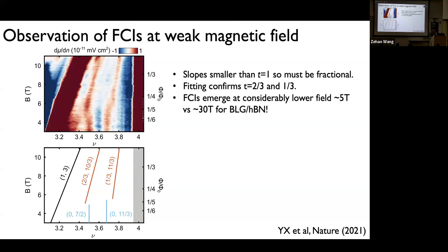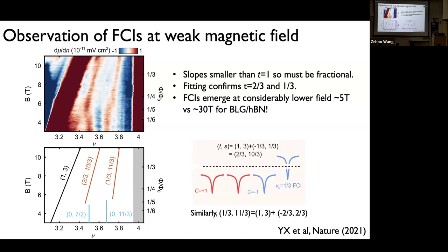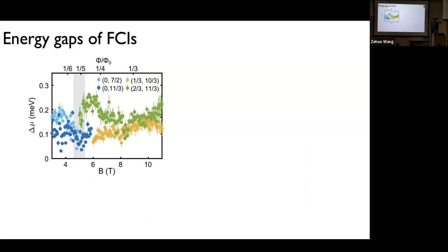And so we argue that this is an FCI state, because the system is very different compared to, say, the Hofstadter problem that I discussed. People saw quantum anomalous Hall effect at nu equals 3, so intrinsically they have their own flat Chern band. And we were quite happy because the magnetic field is, at least in our view, substantially smaller compared to what was needed for bilayer graphene aligned with hBN. And you can also try to back up what the slope and the intercept are if you look at this very carefully. And as I mentioned, the one unique strength of scanning SET is the ability to directly measure the energy gap.